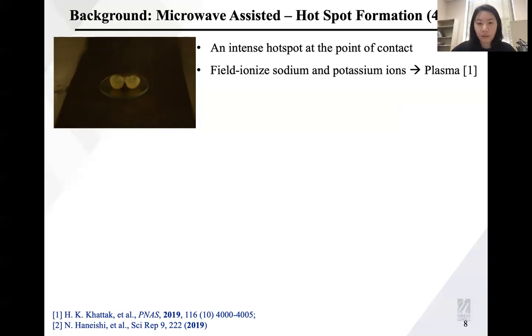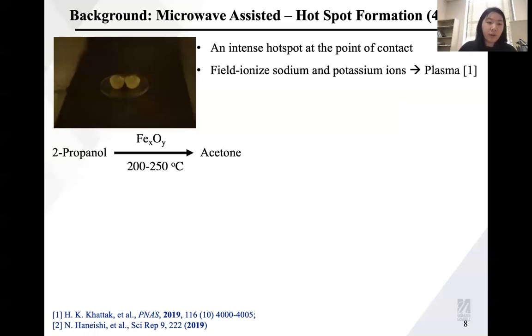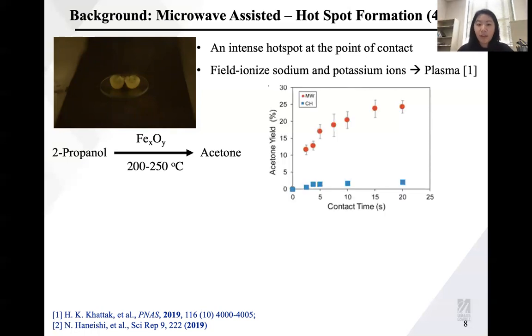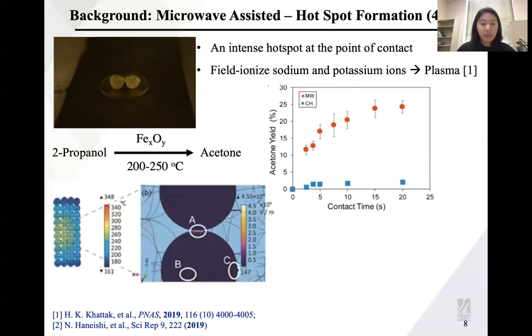into valuable chemicals. And this hotspot can also be used for heterogeneous catalysis, for example, catalyzing propanol to acetone over iron oxide at 200 degrees Celsius. What they found is that under microwave heating, the yield of acetone is significantly enhanced compared to conventional heating. And the hotspot formation inside the iron oxide may be the reason for that high enhancement of the yield of acetone.